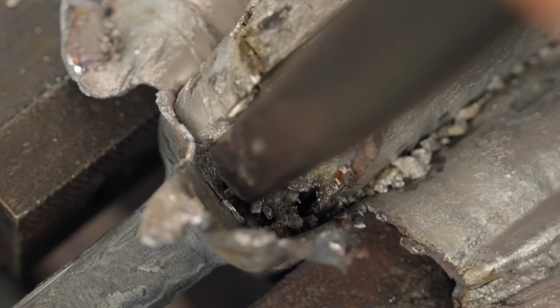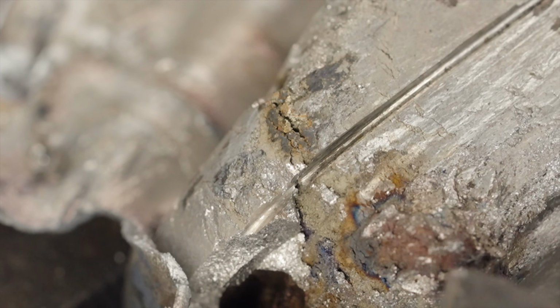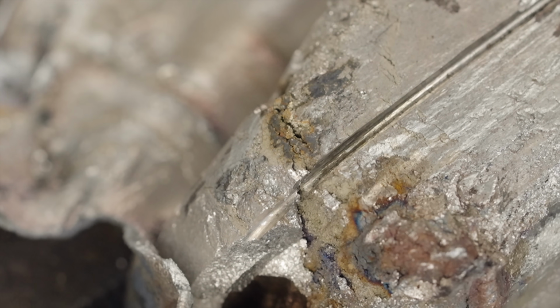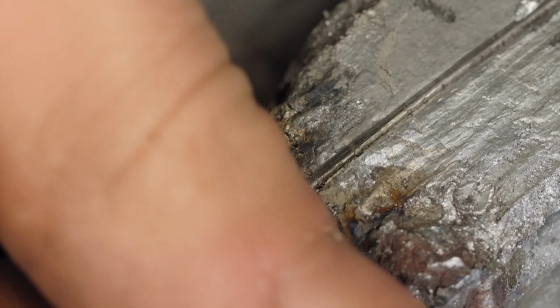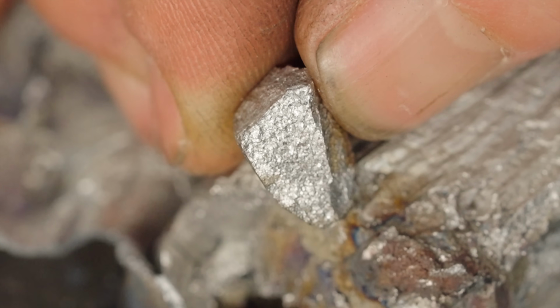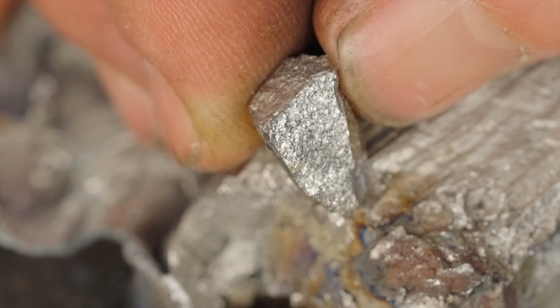As you can see at the back of the billet, there's a very big cavity. It even appears we have a minor crack right here. So something's definitely gone wrong, because the rest of it doesn't look at all cracked. Pretty neat to be able to see the grain structure of the titanium in this little cracked bit.